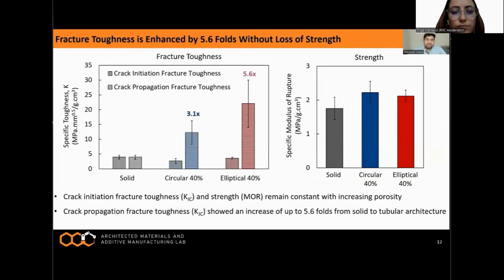More importantly, when we look at the specific crack initiation and crack propagation fracture toughness, the specific crack initiation fracture toughness remains unchanged. This is the good news because that means we can increase the porosity in the material while maintaining toughness. When we look at crack propagation fracture toughness, an increase of 3.1 to 5.6 times from solid material to tubular architected material was observed. And all this happened while the specific strength remained constant. So, the gain is goodness.